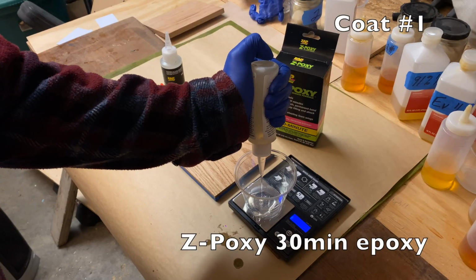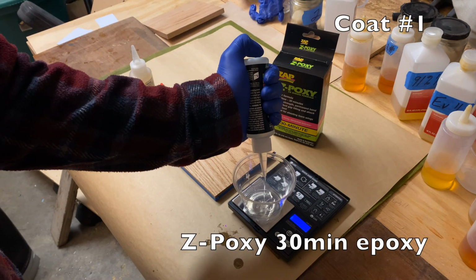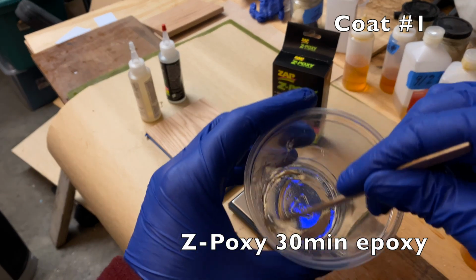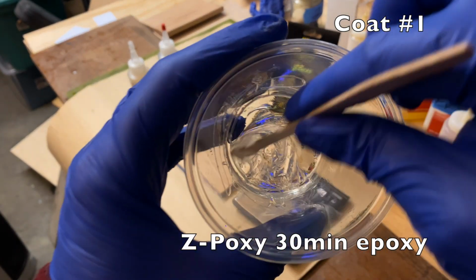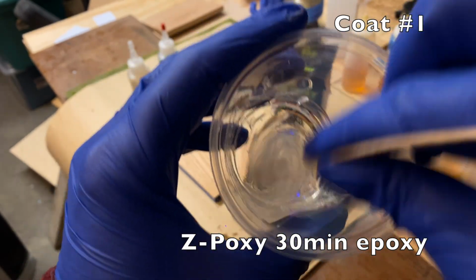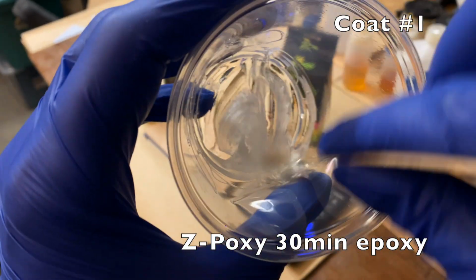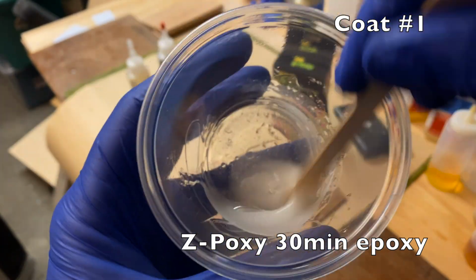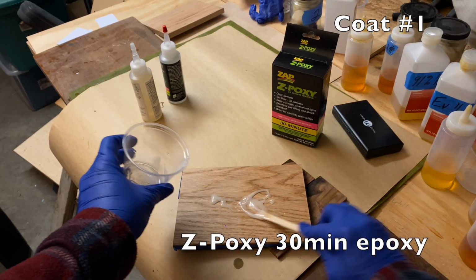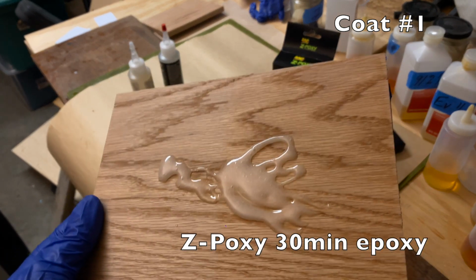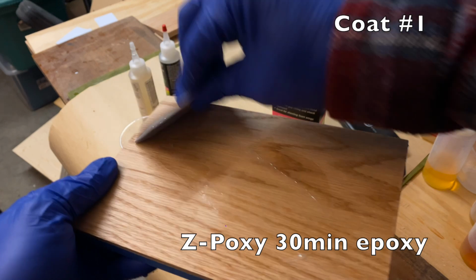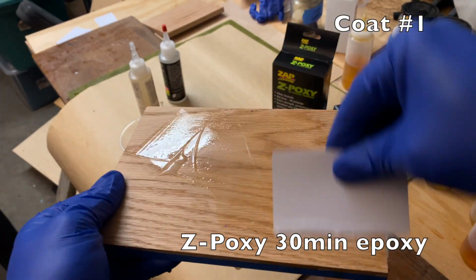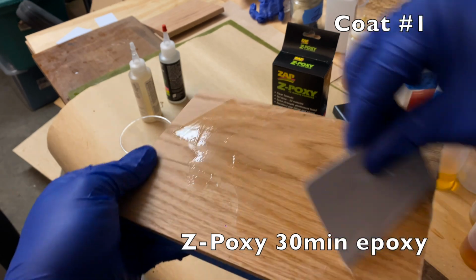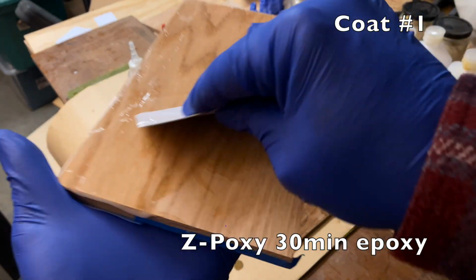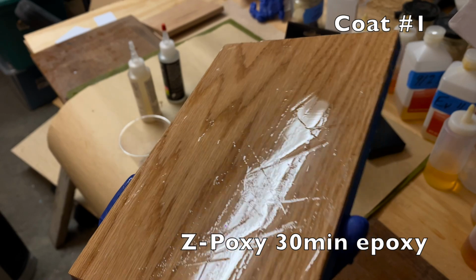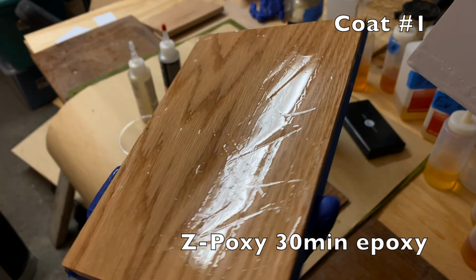This is the Z-poxy 30-minute epoxy, which is marketed more like an adhesive or a bonding epoxy, as the branding touts its extra strength and permanent bonding properties. I paid about $15.50 for 8 ounces, which is 4 ounces of resin and 4 ounces of hardener. And right off the bat, I can tell the consistency is thicker than the finishing resins that we tested earlier. It takes a bit more effort to spread over the workspace, but it's not a big deal. It also seems to coat a bit thicker, so it'll be interesting to see how it sands.